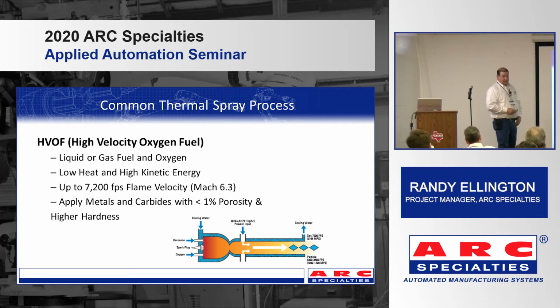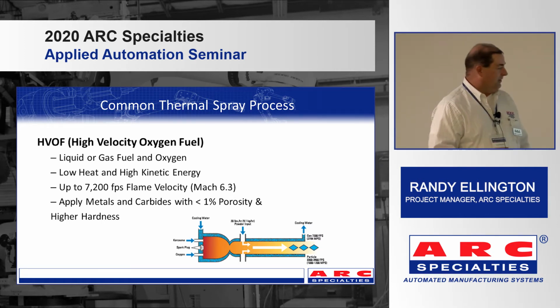Flame velocities, they've clocked them up to 7,200 feet per second. And while I didn't put it up there, most of your materials like carbides, they travel about 3,300 to 3,400 feet per second. And just to put that in relative terms, a bullet coming out of just a standard deer rifle is somewhere around 3,000, maybe 3,100 feet per second. So it's going pretty good.